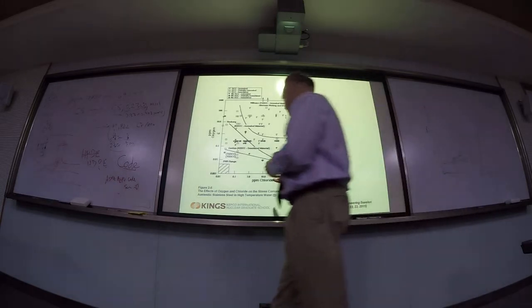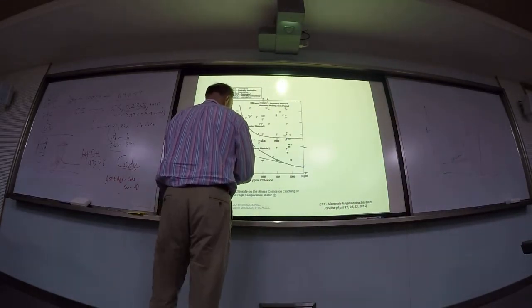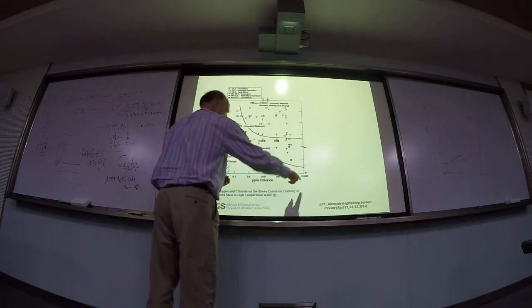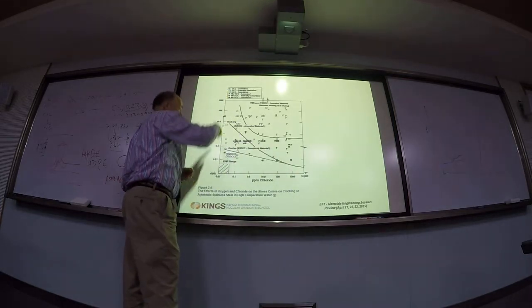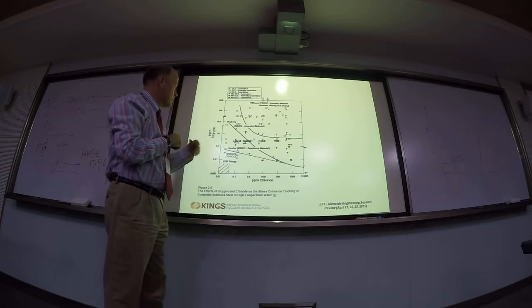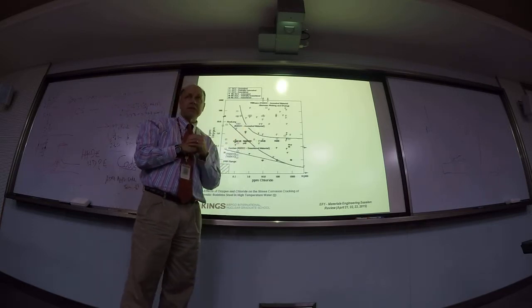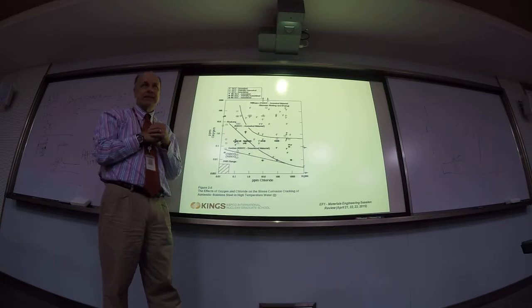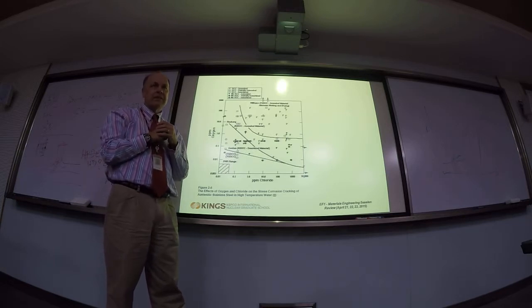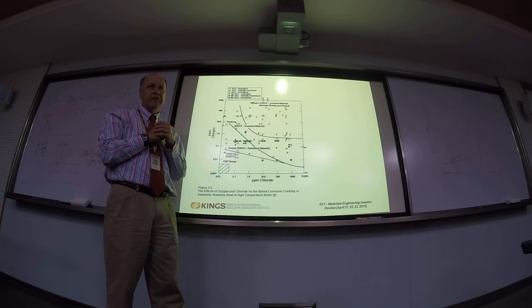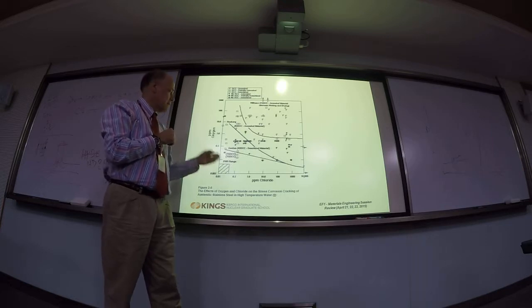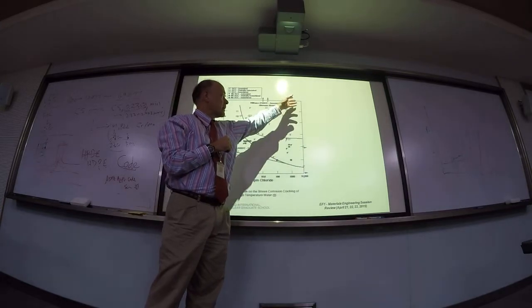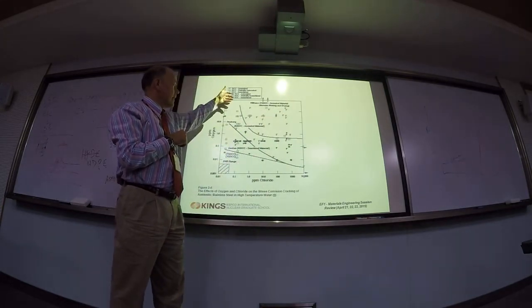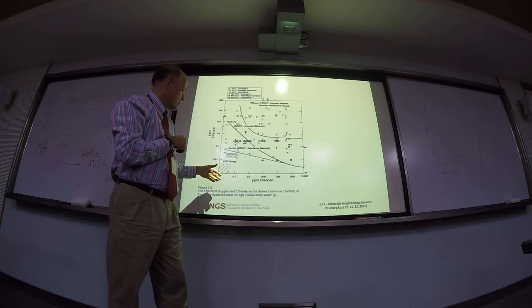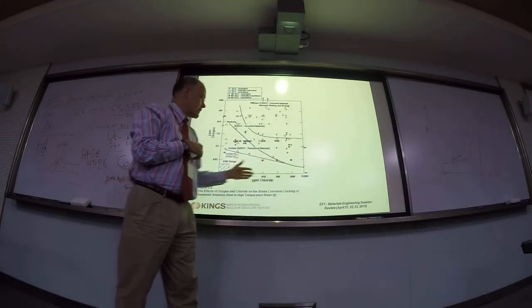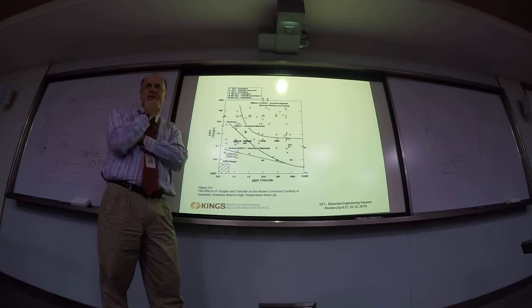So I'll tell you, this one is chlorides this way. Logarithmic, 0.01 to 10,000. And this way is oxygen, 0.01 to 1,000 parts per million. What does this show us? Stress corrosion cracking. Where is stress corrosion cracking a problem? Do we have a problem with high chlorides and high oxygen? Low chlorides and high oxygen? High and high, low oxygen, or low and low? Where do we have a problem with stress corrosion cracking?